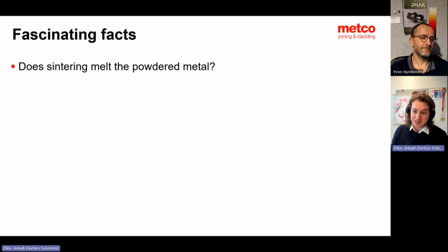Peter, final question to this introductory quiz is, does sintering melt the powder metal? No, typically not. But for some alloys you do. I know you are in the hard metal world. If you have a hard metal as a tool and you want to be able to work with it, you cannot use it if there are pores in it, because then it will be too fragile and it will break. So therefore, you typically sinter in semi-liquid state, so you have up to 20% liquid phase in the beginning of the sintering.